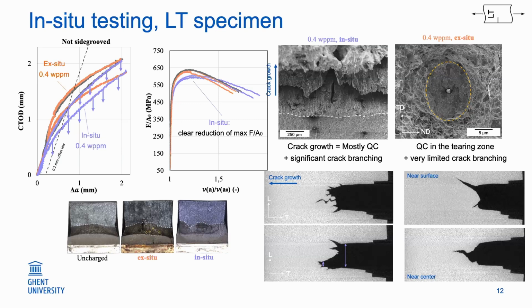And we also see in the CT scans that we have very pronounced crack branching. You can also see it here on the top. There's actually multiple cracks growing during the test. Here we have one from the edge of the specimen, and this is more from the middle. These are very sharp cracks, but it doesn't really show in the resistance curve. And of course, we are measuring with the double clip gauge method, so we cannot really capture this crack opening when we are actually seeing the crack opening here.